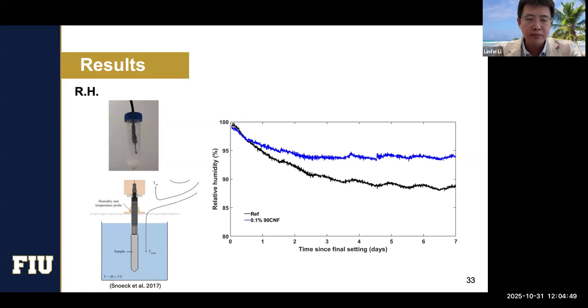So finally, we changed the setup. Basically, we crush the samples into powder, put that into a tube, set up the sensor in it, and then measure the relative humidity in the powders. We started after the final setting time, and on the right hand side, you can see that adding even 0.1% of CNFs can keep the relative humidity at about 94% for up to 7 days in the isolated system, which is apparently much better than the reference samples.